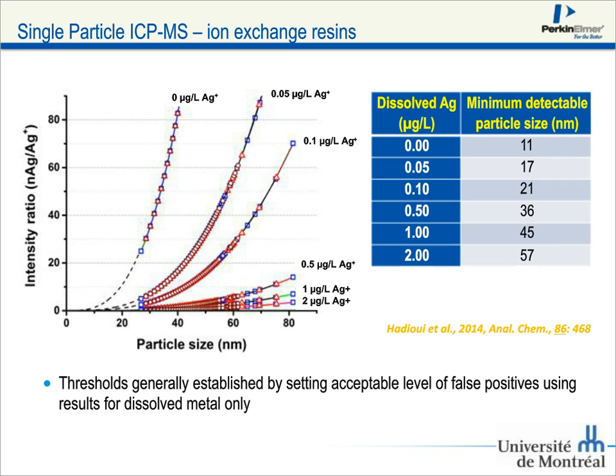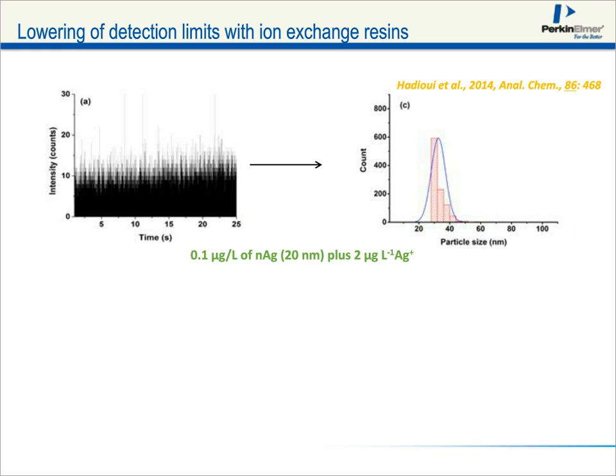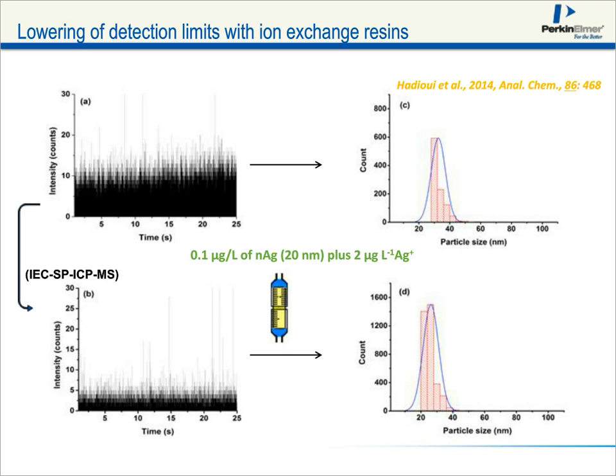And so let me show you what happens when we do that. We're trying this in single particle ICP-MS mode, and you see for a 20 nanometer silver nanoparticle, we can get a peak, but we're missing some of the information at the lower particle sizes. If we run this through a resin now, the ion exchange resin, we essentially remove that continuous noise or the background signal, and we can get a much nicer, clearer signal for the nanoparticle.